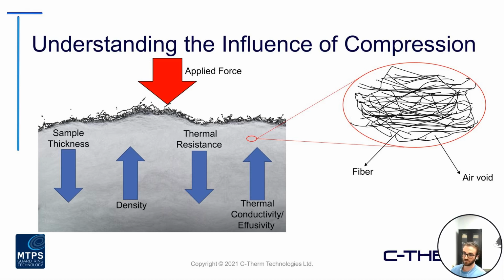Air is an extremely good insulator, and therefore the more air that is present in that measurement zone, that's going to result in a much lower effective measurement. If you compress and densify that sample, you're moving that air out and away from the active area. Therefore, this is how you're getting at those higher thermal properties.